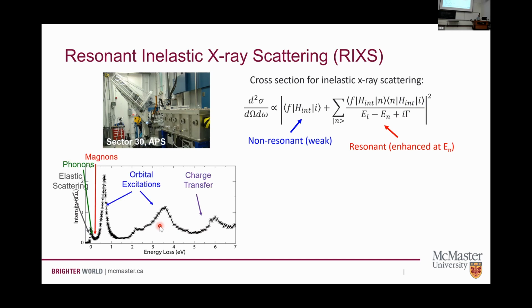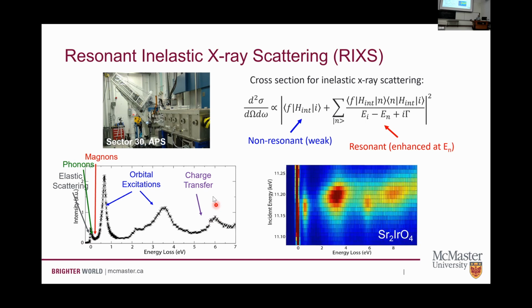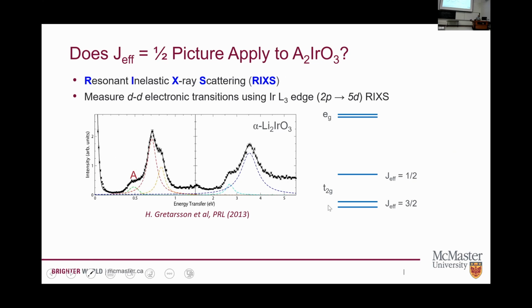And this lets us look at some elastic scattering here at no energy transfer, phonons at very low energy transfers, magnons or magnetic scattering at low energies here. Then as we move up in energies, we see these orbital excitations between different d levels and eventually charge transfer as we're moving electrons from oxygen to iridium. Okay? And if we vary the incident energy, we can go through these resonances, and we can use this to actually assign these different features to not just the iridium, but also to different orbitals. Okay, so it's kind of a neat technique in that sense.